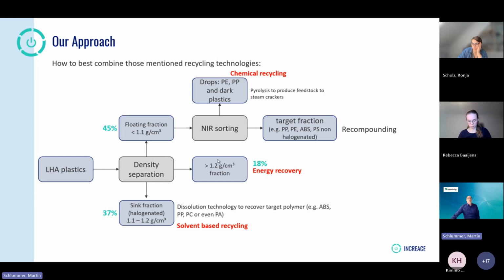We have a very high density fraction, which still needs energy recovery through incineration. And we have another roughly 45% coming from the floating fraction, which can be separated by further NIR sorting into something which can be fed directly into high-value recompounding, for example the polypropylene, polyethylene, ABS, PS, non-halogenated fractions. And we have a drop fraction, which also contains polyethylene, polypropylene, and other dark plastics, which can undergo so-called chemical recycling: pyrolysis plus upgrading plus steam cracker.